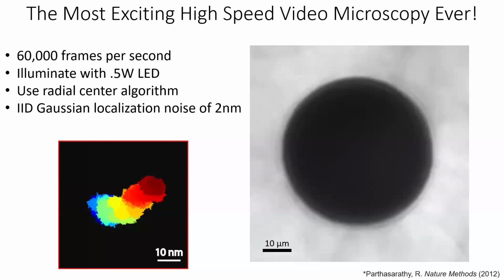And this is the reason why we use such a big particle. If you use a big particle, the information is spread out over a large region of your image, which means that you can localize it very well to a sub-pixel resolution. And the thing that is obvious but hard to reason to yourself is we all think about small particles as subject to much more thermal fluctuations. And they are, on the scale of themselves. However, large particles move farther thermally. A bowling ball at room temperature is jiggling around much, much more than an atom. It's just that the atom is moving a lot more relative to its scale.